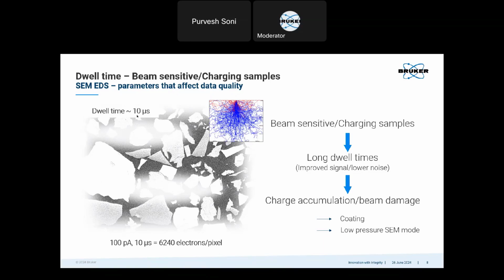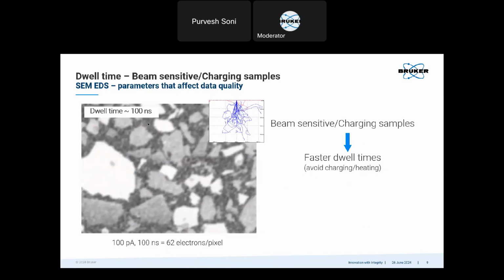Now, for, let's say, 10 microseconds and 100 picoampere, we'll have about 6,000 electrons per pixel. And if we decrease the dwell time from 10 microseconds to 100 nanoseconds, then we'll get 62 electrons per pixel. So simply by decreasing the dwell time, the number of electrons reaching the sample per pixel is now much, much lower, 100 times lower. This will avoid charging and also sample heating, and this may be better for the sample, but then the signal to noise ratio is very bad. So then you get maybe very noisy SEM images, and sometimes even no EDS signal.